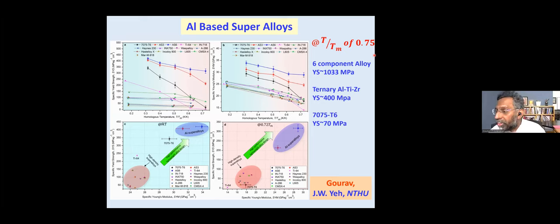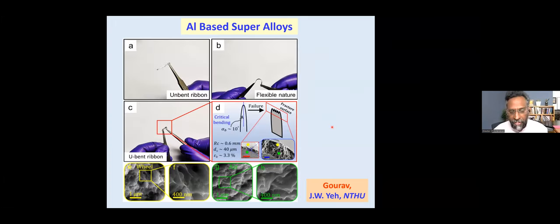When you look at the strength, the alloy has about 1000 megapascal strength. In comparison, the conventional aluminum alloy called 7075 has only 70 megapascal. You can see this is more than 10 times, 15 times. Okay, that's the beauty of these materials. So you can generate, by this kind of a concept, very strong materials useful for high temperature applications or even room temperature applications. That basically means you are able to generate new alloys with better properties so that they can replace the existing alloys and make them much cheaper in terms of the cost of the alloys. So a lot of exciting applications.